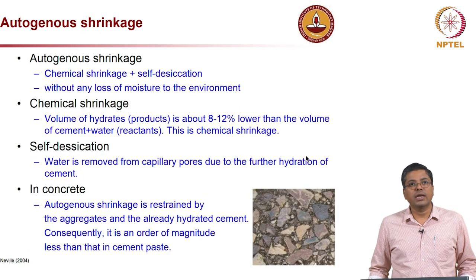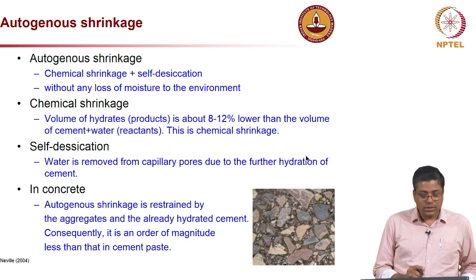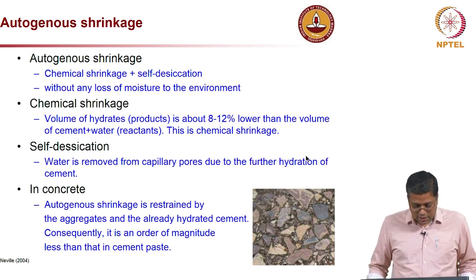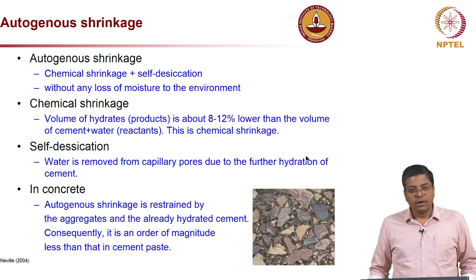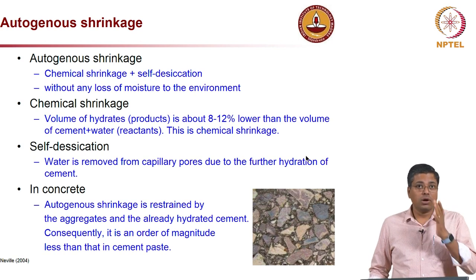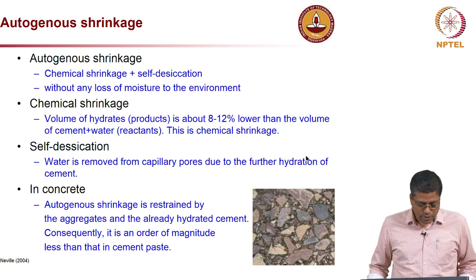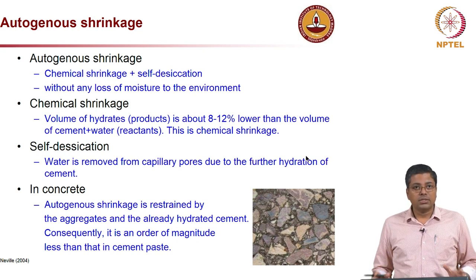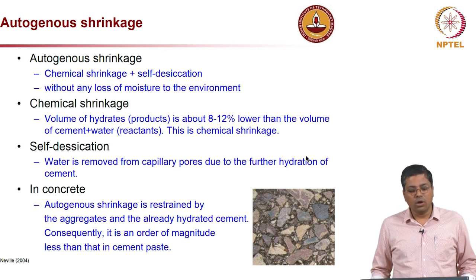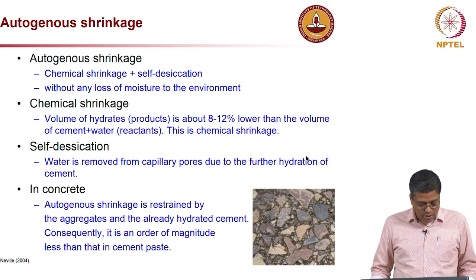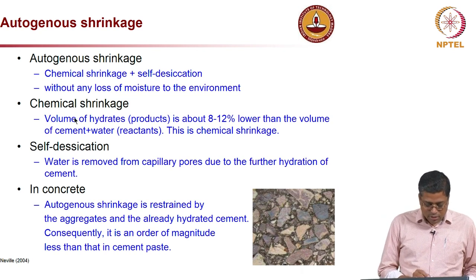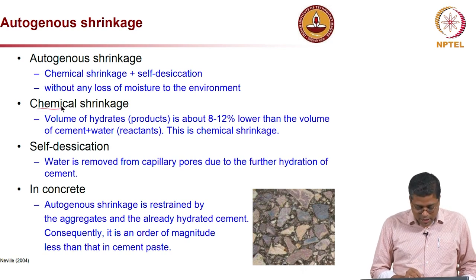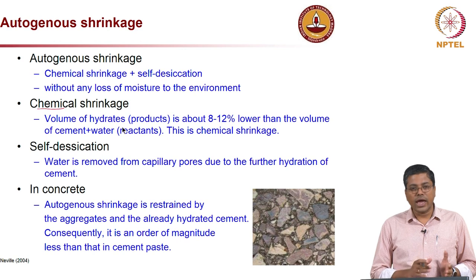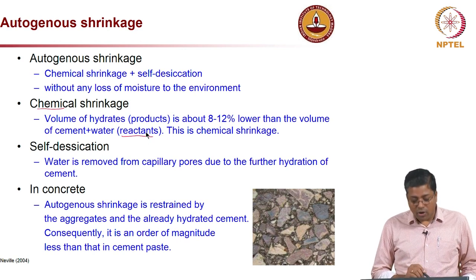Now, another shrinkage mechanism is autogenous shrinkage, which is typically a combination of two processes, chemical shrinkage and self desiccation. And the main thing to note here is that this happens without any loss of moisture to the environment. Okay, there is no drying or anything like that happening. Now, what is chemical shrinkage and what is self desiccation? Chemical shrinkage, as the name suggests, is due to some chemical reaction, which involves reactants and products, of course, and the reactants have a volume which is more than that of the products. How much? About 8 to 12%.